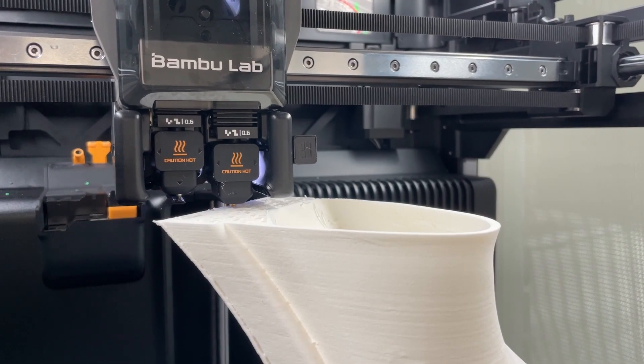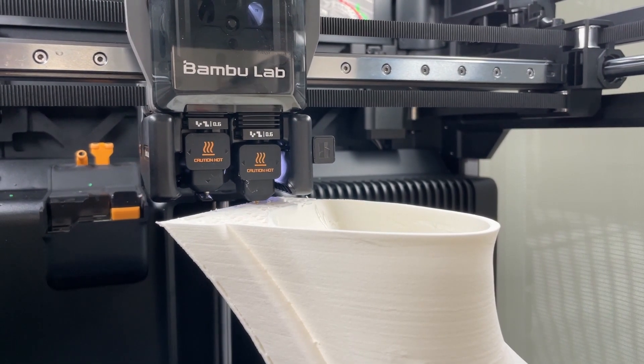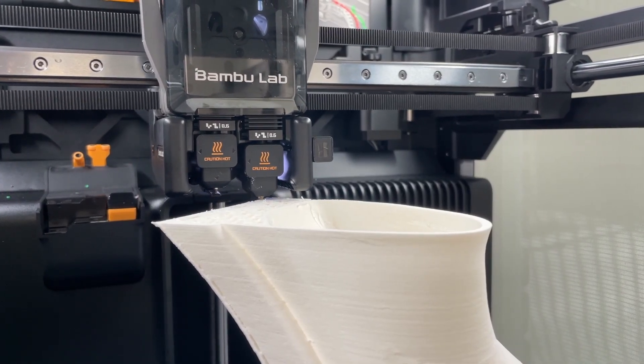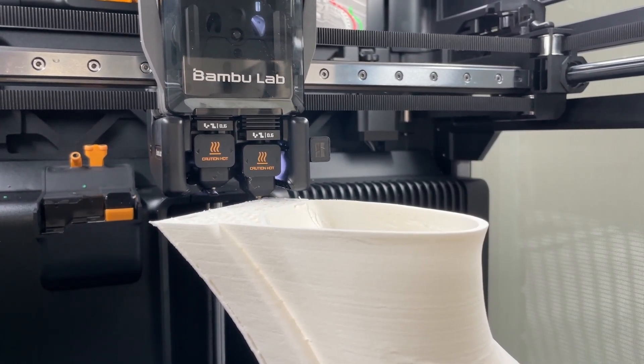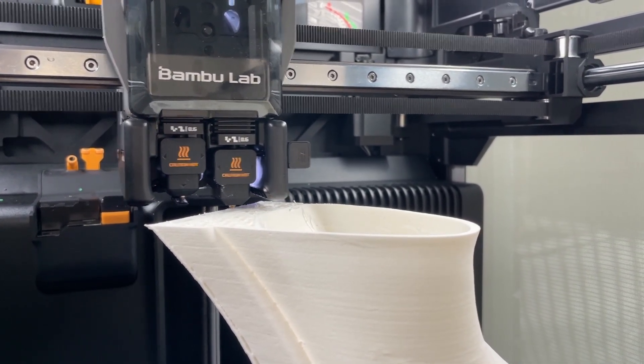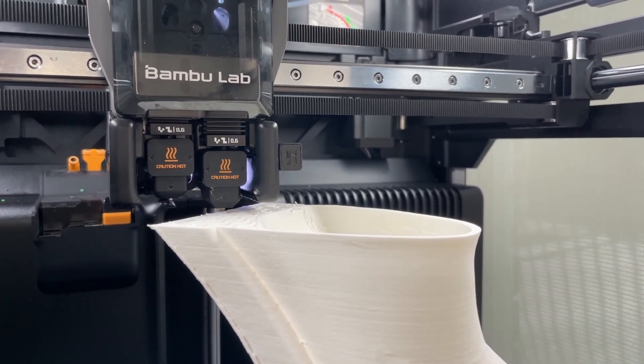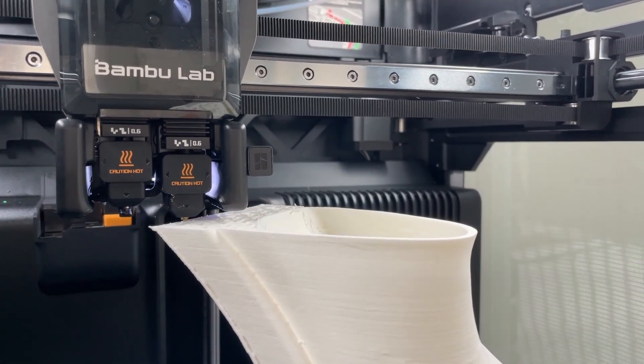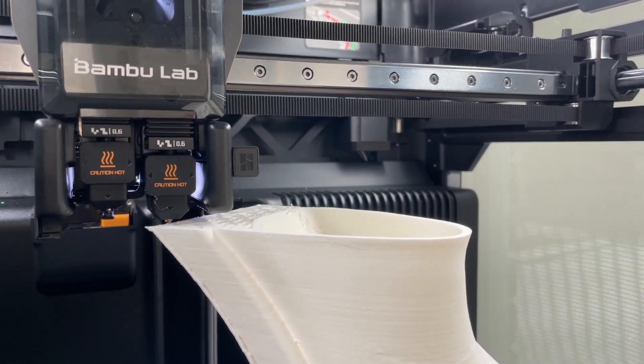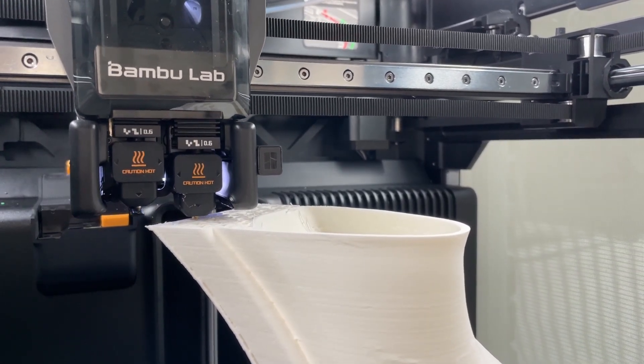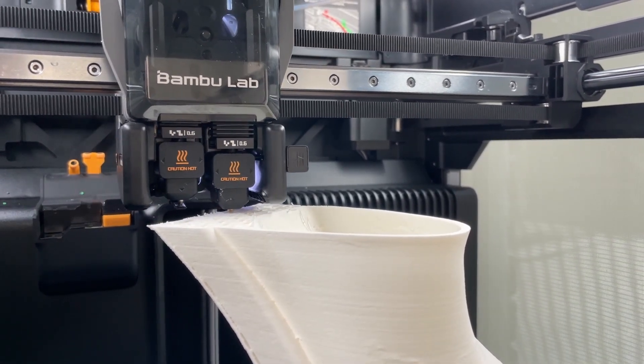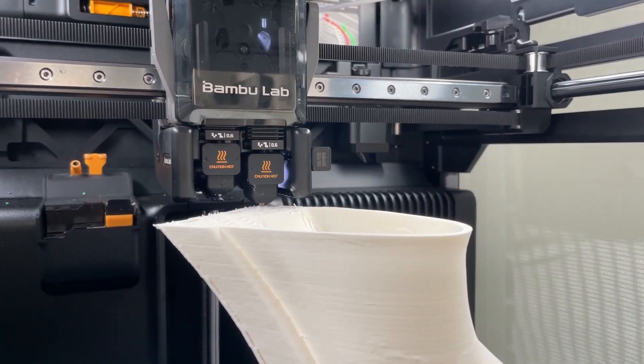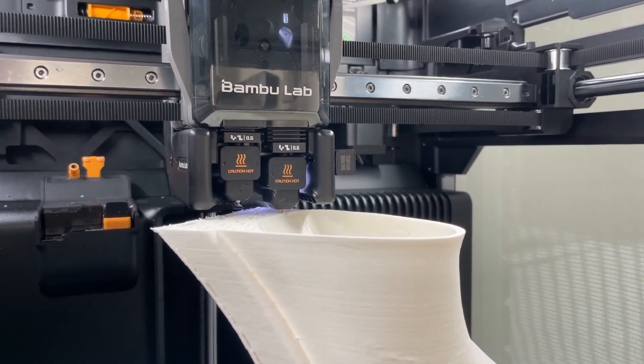As I mentioned, I like to 3D print shoes with foaming TPU, an example of which I'll provide a link to in the description for this video. Foaming TPU only becomes soft after exiting the extruder via foaming, so it is stiff enough to print with at a decent speed and without any workarounds. It prints just fine on my Bambu Lab H2D.